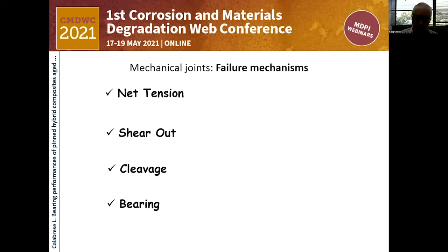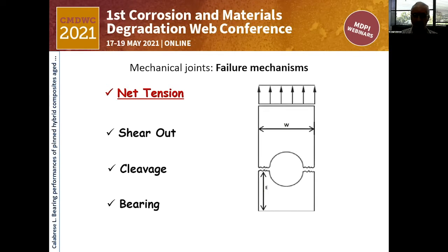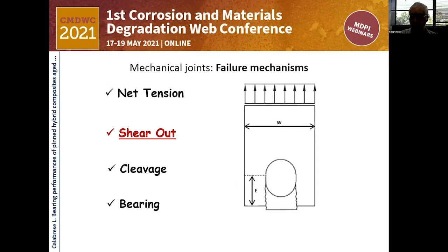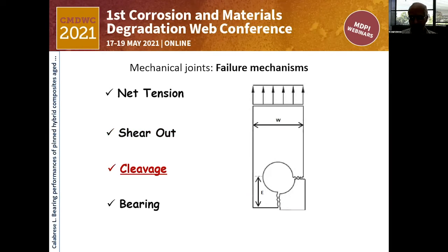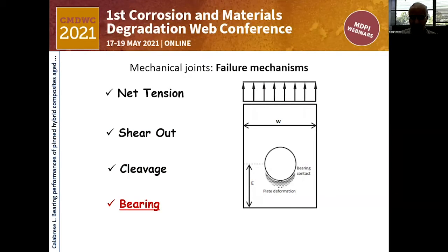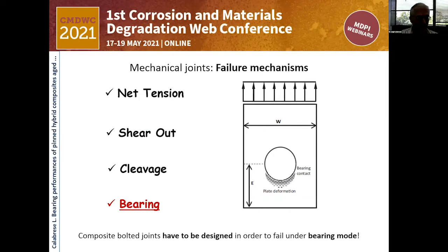Why this idea? We know that composite joints are characterized by different failure mechanisms. We can observe a net tension fracture, when the cracks start and propagate orthogonally to the load direction; a shear out fracture, when we have a fracture of the joint near to the edge of the samples; a hybrid fracture, as cleavage, that involves net tension and shear out mechanisms; and the usual bearing fracture, where we have the collapse of the composite material just behind the pinned joint. For all of them, the failure mechanism is influenced by the geometry of the samples.